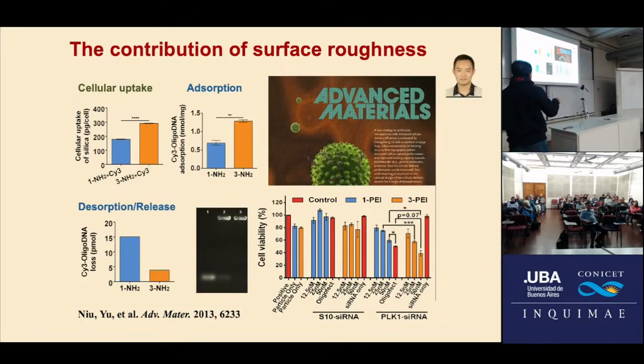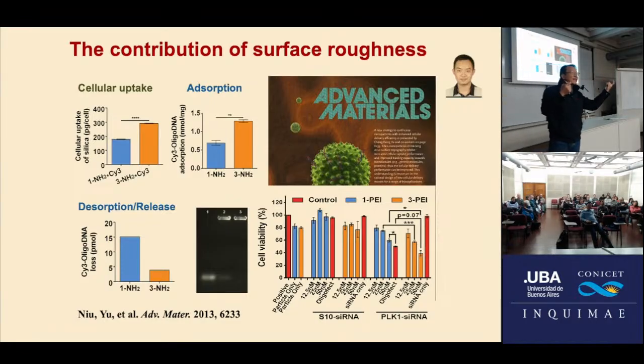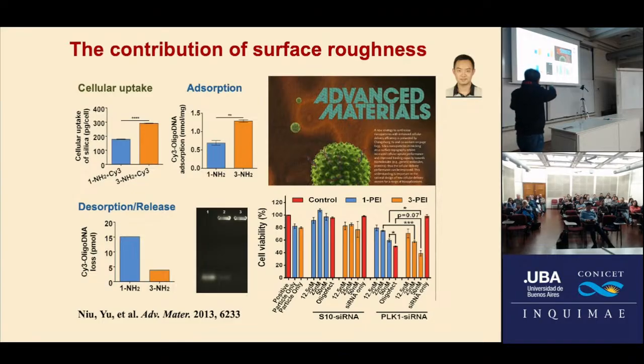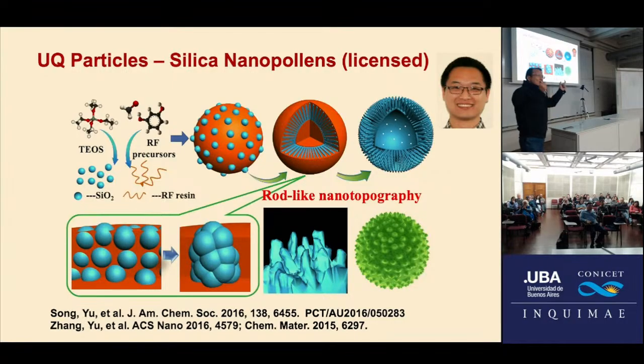So this is the first example, as I mentioned before. We can use a big particle and a small particle. One is negatively charged, the other is positively charged. Mix them together, and spontaneously this particle can be formed. We have demonstrated that this rough morphology can increase adsorption towards a target molecule, slow release, and also the cellular uptake can be increased, so that, for example, in this case, the gene silencing performance can be improved.